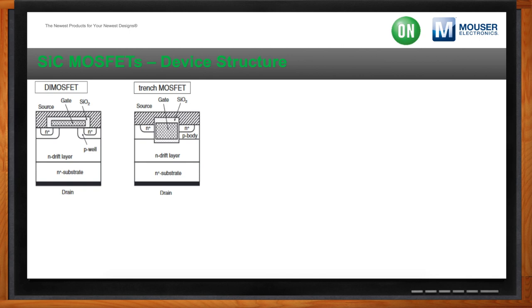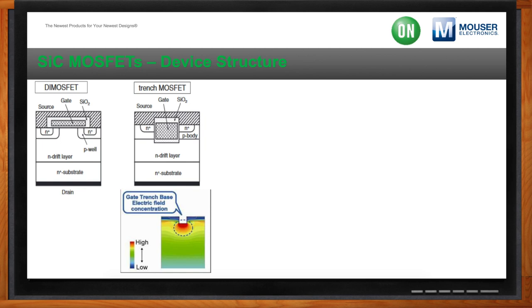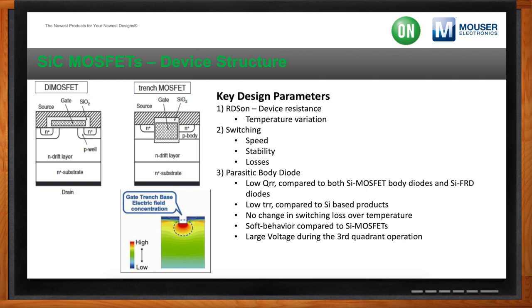The biggest thing to be aware of in the trench MOSFET is that you get an extremely large electric field on the gate. The gate oxide on silicon carbide MOSFETs is the key parameter when you create these. And when you have a very large electric field on that gate, that makes the device susceptible to breaking.